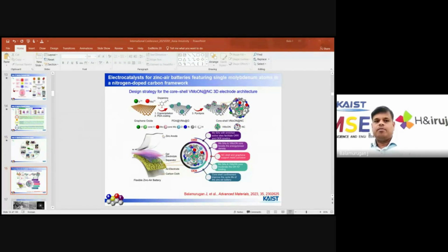So we have communicated some papers, maybe published some papers, like a molybdenum-based single atom catalyst. This is the design strategy. You can see we take the graphene oxide-based material and do the co-precipitation by PDA, and finally make the molybdenum single atom.